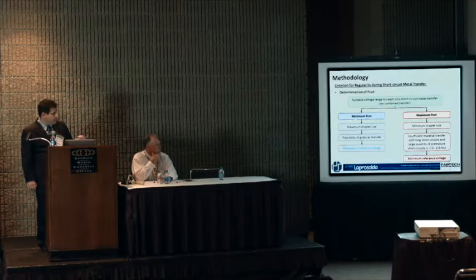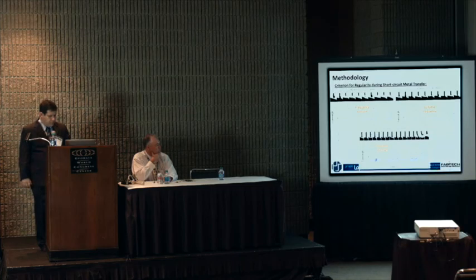So we have a minimum, because otherwise we end up with a big droplet size and globular transfer. As well, you must have a maximum frequency, because otherwise you start getting too drastic short circuit transfer, too much material for that weld pool. You end up rolling the wire itself and you get really messed up. Let me show you the